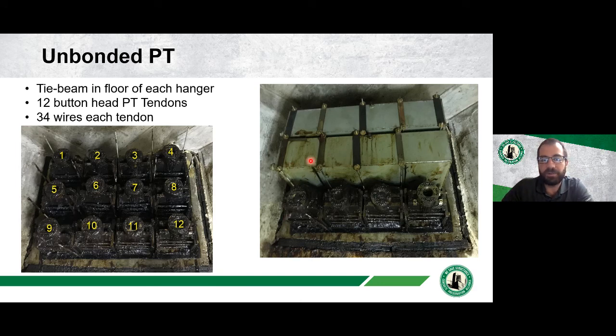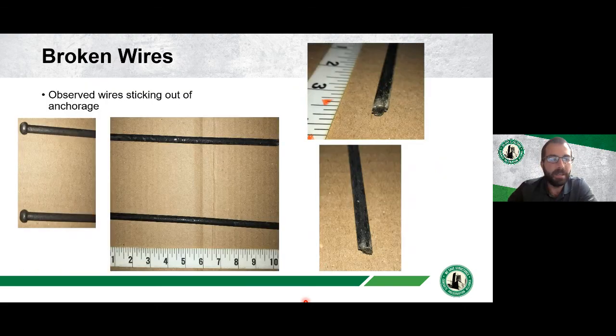And there are these grease boxes here that are applied over these tendons to keep them from corroding. But because these structures are below grade, there is a risk for water getting in there. And we were asked to look, is there a risk for corrosion on these strands? So one thing we looked at, there were a couple of broken wires sticking out, and we pulled those out, and you could see that there were some failures of the strands. It looks not really like a corrosion failure. May have been a failure during stressing.